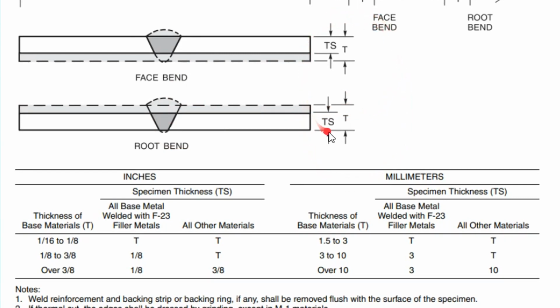This chart's a little bit confusing, but what they're telling us is the finished coupon thickness compared to the total thickness of our original base metal. If we're doing some smaller, thinner base metal, we can get by with a slightly different thickness. But with 3/8 and over, basically the TS is going to be the same as our base metal. It's going to be 3/8. Now, if we had a 1/2 inch thick metal, we could still get it down to 3/8 of an inch. But in this case, we're dealing with 3/8 of an inch metal, and that means our specimen thickness needs to stay 3/8.